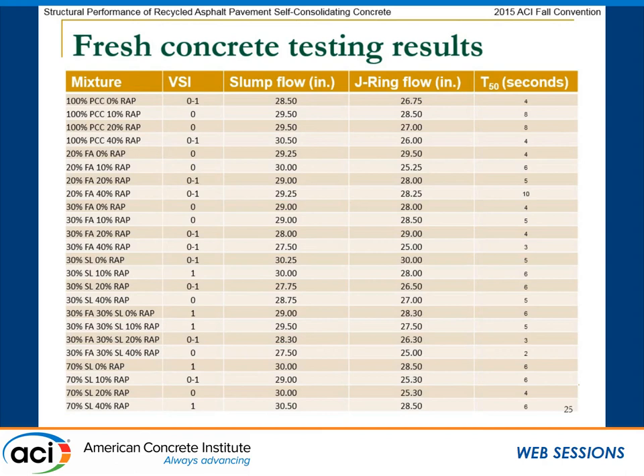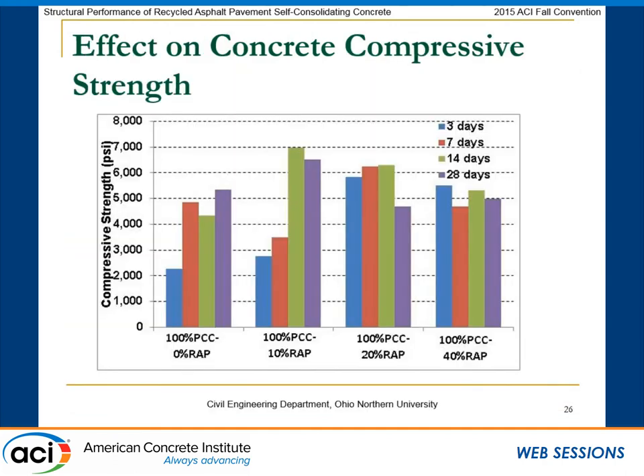For T50, you had very reasonable scores, but you can see here that the mix with 20% fly ash and 40% RAP has a rather high T50. But in general, the T50 readings were good.